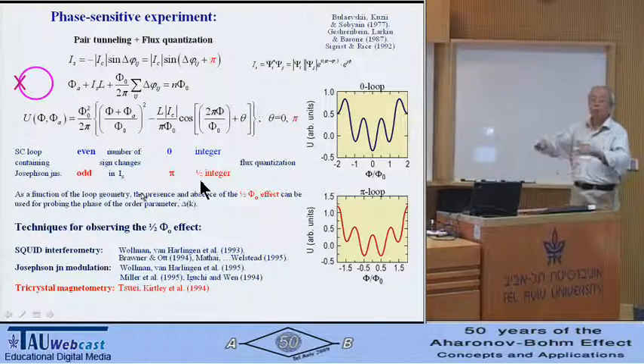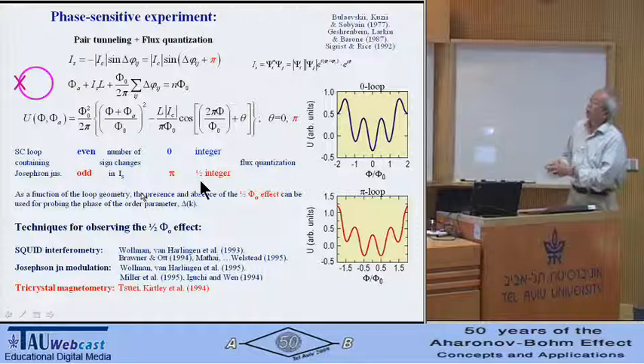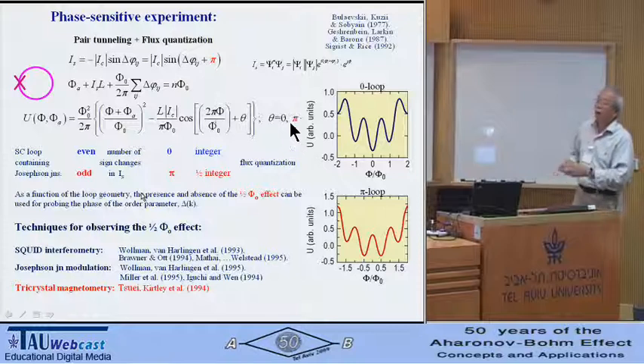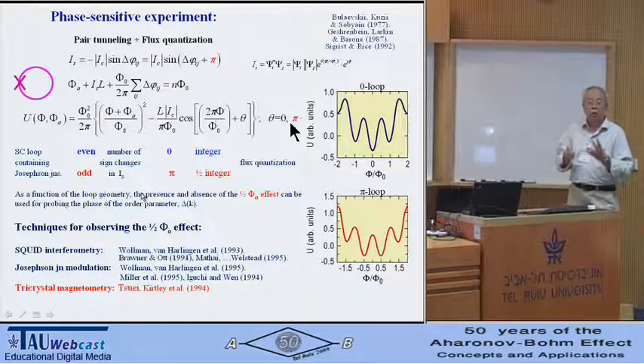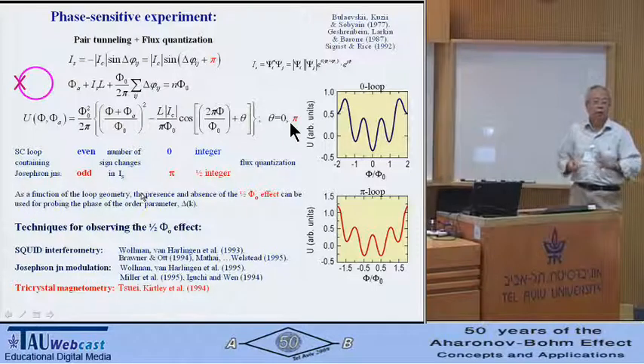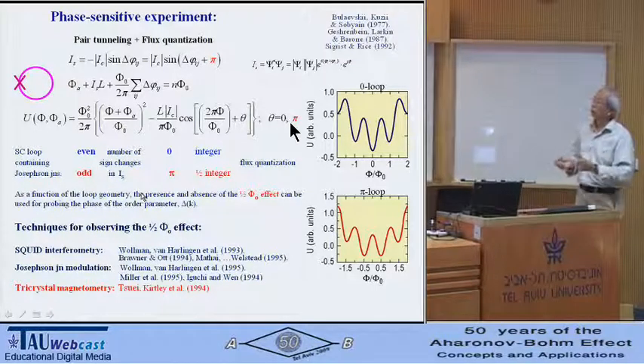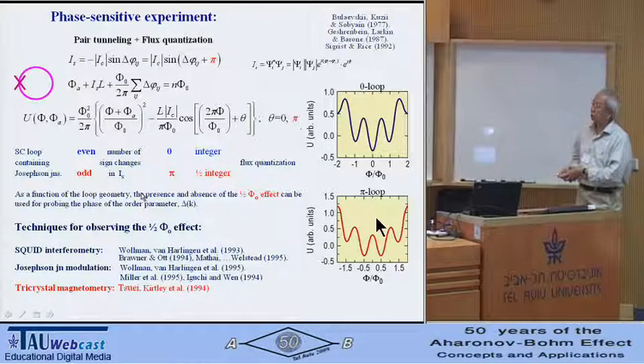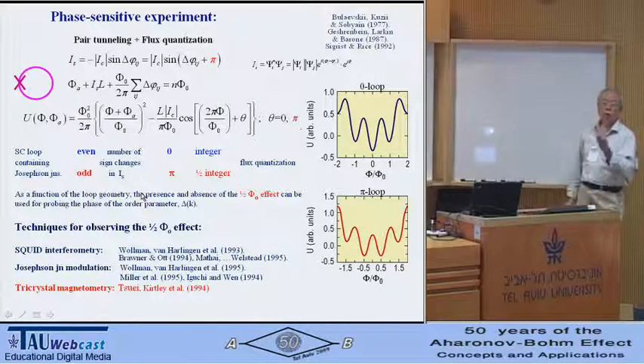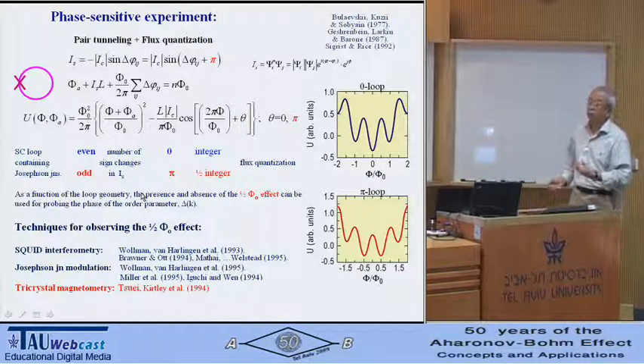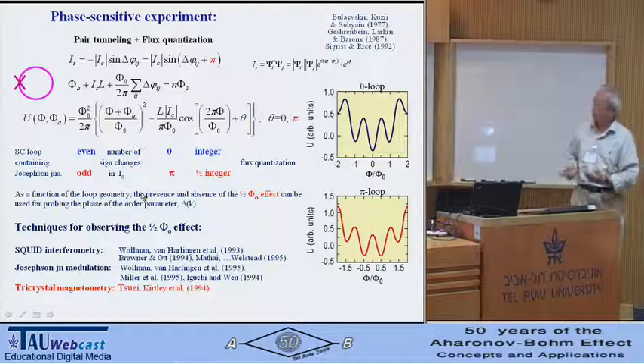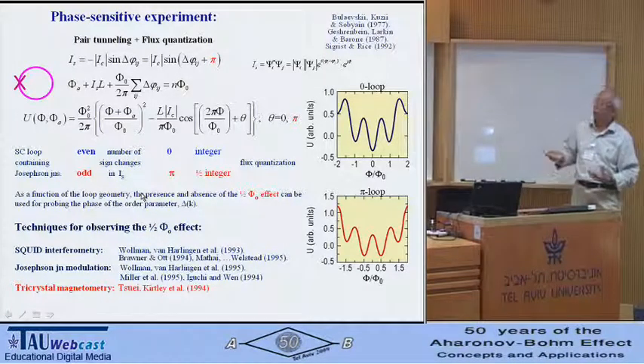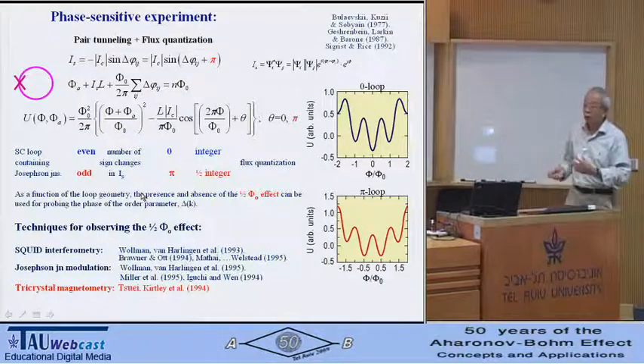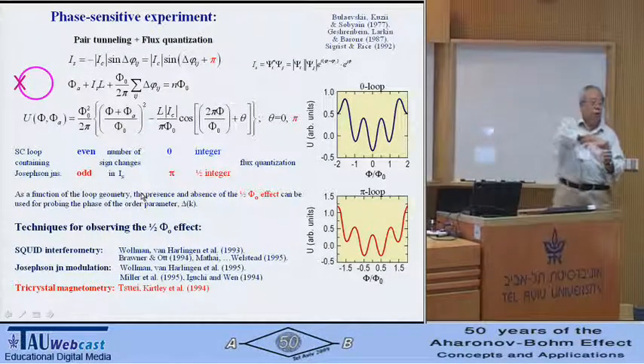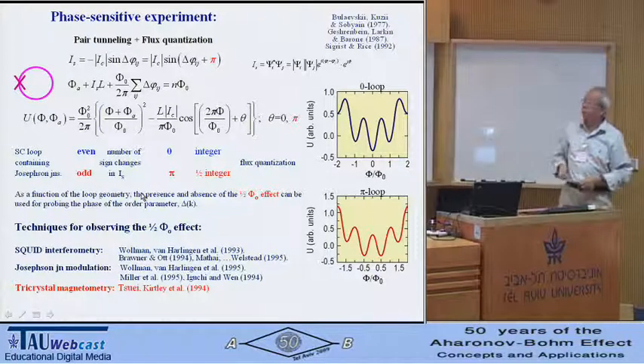That would lead the system to be frustrated and want to relax, to compensate the energy of the Josephson junction, as you put a pi in here. That would cause the system to spontaneously generate a current that produces a half flux quantum. In here, you have a plus or minus half flux quantum threading the loop. This is a doubly degenerate, time-reversed ground state of the pi loop, and that corresponds to the supercurrent flowing in the ring clockwise or counterclockwise. The energy is the same.